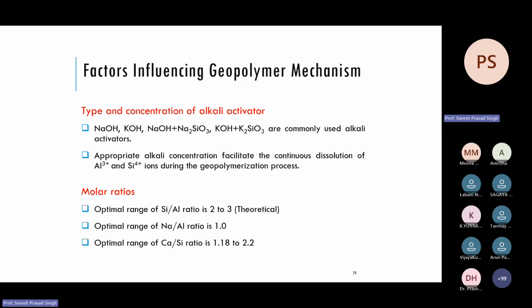The release of silica from sodium silicate is easier. The bonding between silicon and oxygen here is very weak. So if you use sodium silicate in conjunction with sodium hydroxide, you will get a lot of silica ions, which will give the optimal silicon to aluminum ratio, and that will give you better strength. So for appropriate alkali concentration there is a lot of research, cation diameter and all these things. But in a nutshell, it depends upon the concentration and type of the alkali and the source. This is the secondary source of silicon: if you add sodium silicate or potassium silicate in conjunction with sodium hydroxide, that will be a secondary source of silicon to the structure.